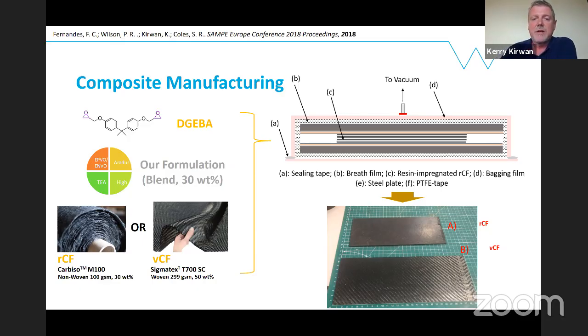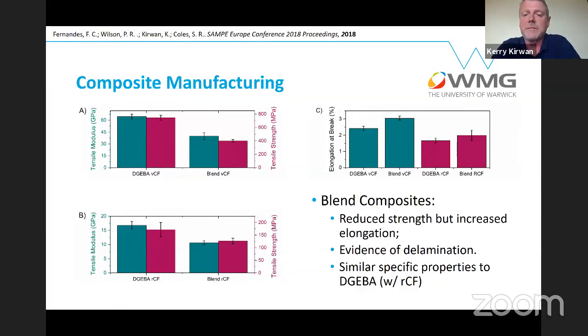But essentially, we made some very nice composites, and when you start testing them, what we again found was, as you might imagine, the strength and the stiffness wasn't as good for the blended ones, but actually the impact performance was better. And also, when you do the traditional composites approach, which is to look at the specific properties, we actually found our bio-based DGEBA recycled carbon fiber composites perform very, very well compared to virgin carbon fiber. So that was an interesting thing.